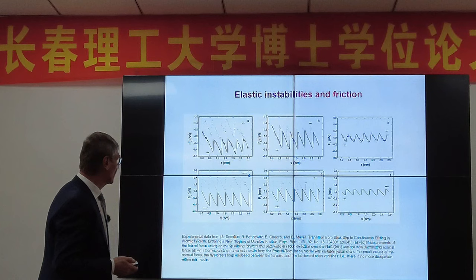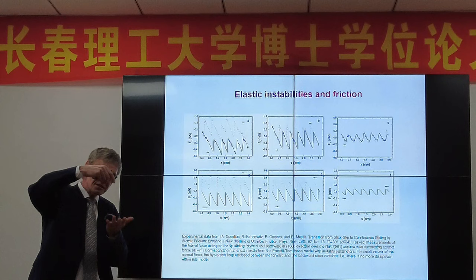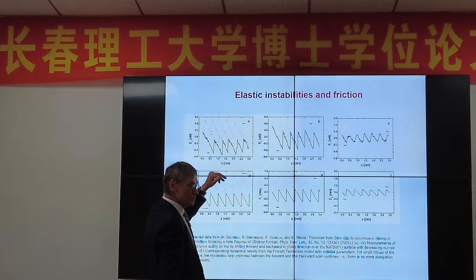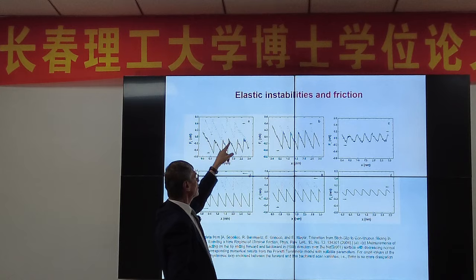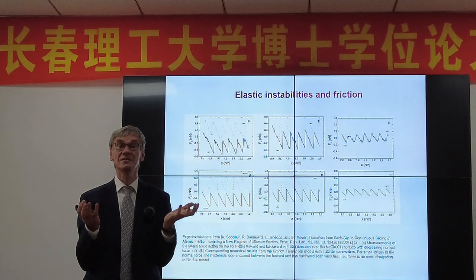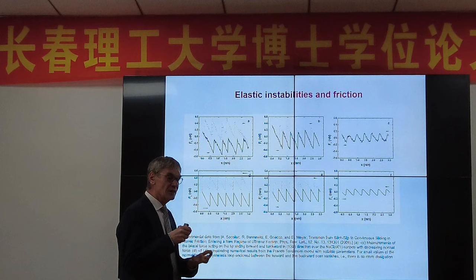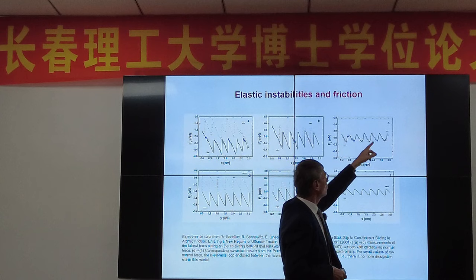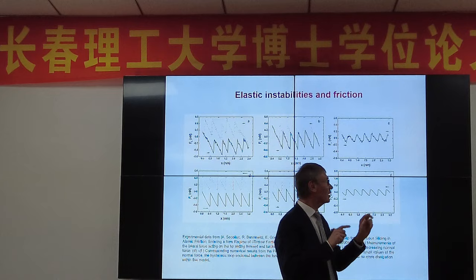These are experimental data with the atomic force microscope. One has a tip on the atomic plate, and the force is periodic with jumps, and if you move back, then you have another curve. There is some area enclosed by the curves by moving forth and back, and this enclosed area is dissipating energy. But if the stiffness or the potential gets smaller, weaker, then you have an undercritical situation where the movement forth and back is completely the same. You move along the same curve, so there is no area enclosed and no friction.